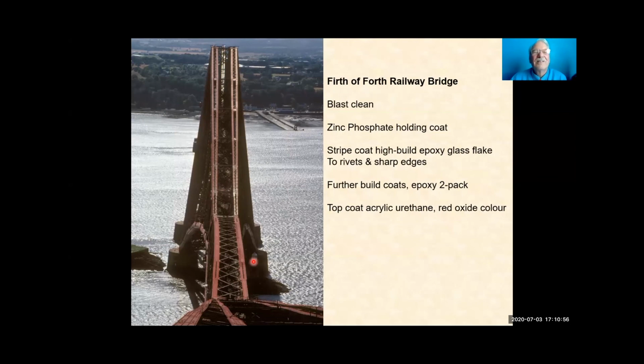And the challenge has always been to see whether it's possible to paint the Forth Railway Bridge with paint that lasts more than 20 or 25 years. And it has now been achieved. And what they did was to blast clean to SA 2.5. They put on a zinc phosphate holding coat.